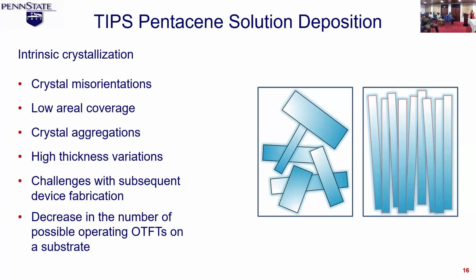So we want to avoid crystal misorientation. Low areal coverage, again, these are crystals on the substrate, means that you can't have the best performance out of what you have here. Crystal aggregations are when the crystals develop on top of each other. We don't want that either. We don't want too much variation in the thickness of the deposited crystals. Essentially, we want to ensure that our device performance is good. Right? So the different deposition techniques that I use typically want to achieve these.